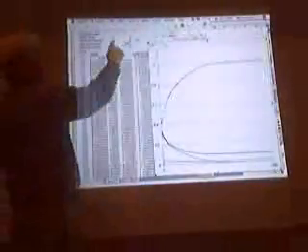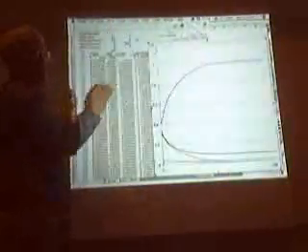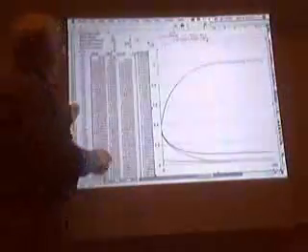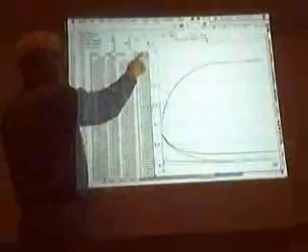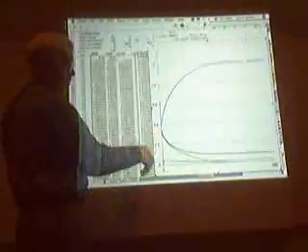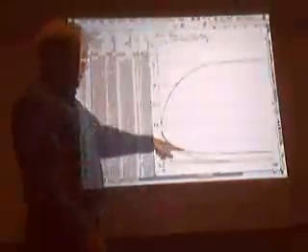Okay, so these are the various rate constants, and notice the ones involving nucleation are set to 0. Several of them are set to 0 because I don't think they're important. And here, we start with a little bit more of big ones than small ones, right? Of the green, big, and the red, small, and a certain amount of monomer in solution. And as you numerically integrate it, the red goes away faster than the green and goes to 0.